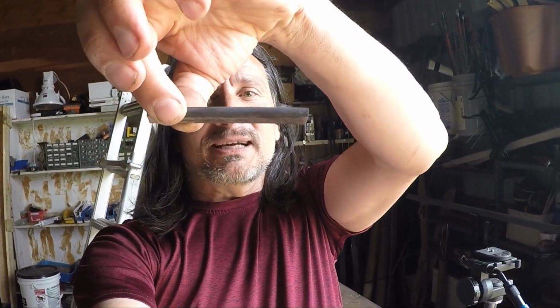A lower tempering, which means I can get a higher RC, and it's 56. That was almost as high as the top, even as quenched. As quenched highest was between 58 and 59, so I only lowered it about 3 points, and it still succeeded and did not break. So very rudimentary test. It's not scientific or nothing, but at least it gave me what I could do in a forge that's just propane, going by a magnet testing to see if it's up to the proper heat, with no special furnaces, not really a controlled environment.